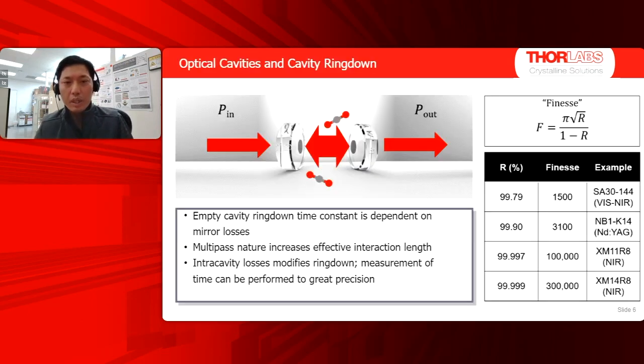So why do we care about making these cavities? Well, it turns out it's a very nice way to do trace gas detection. You're trying to detect very small amounts of absorption, which ordinarily you would do as a radiometric measurement. So you're just trying to detect a small absence of light from the input beam. And that's actually a very difficult measurement to make. So this cavity ringdown approach allows you to convert a radiometric measurement to a time measurement, and you can measure time with great precision, and that actually gives you a lot of its sensitivity. And couple that with the path enhancement, you have a very sensitive trace gas detector.